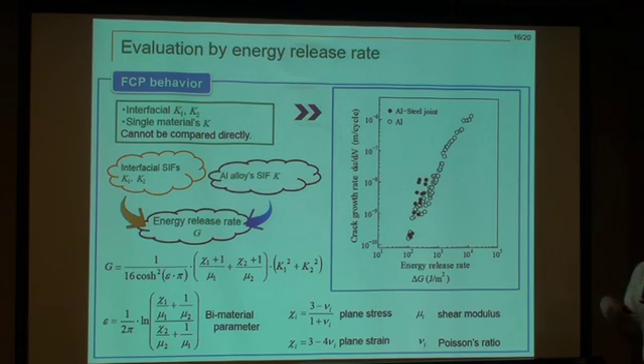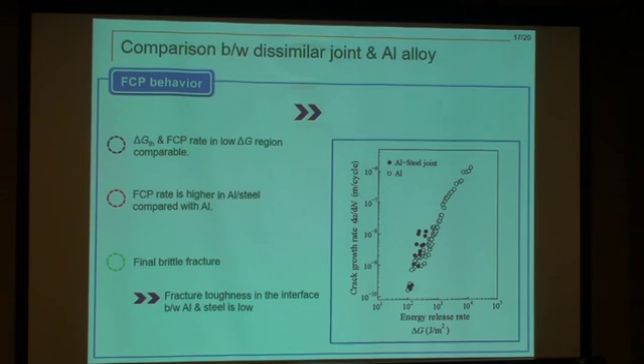This is the equation that we have used in our study. As you see in this equation, you have to use a so-called bimaterial parameter and some other material constants. And this is a comparison. This is a result of our test comparing the dissimilar welding joints and the aluminum alloy. Here you can see that near the threshold area, or in the low delta G region, the crack propagation rate in the dissimilar welds and the aluminum alloy itself are comparable, not so different from each other.